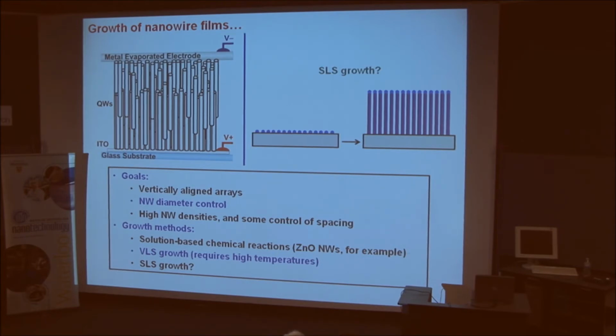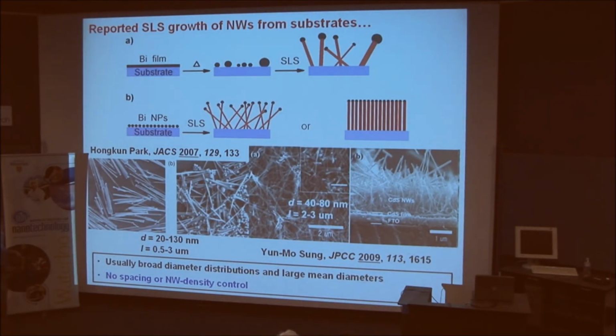So can we do this by the SLS method? Well, there are a few reports in the literature in which this has been done or attempted. And those attempts start with a substrate, and a bismuth film is then deposited on the substrate. And then the film is broken up by thermal heating to give a series of catalyst particles. But actually, this cannot be done. There's no way to control particle size with this sort of strategy.